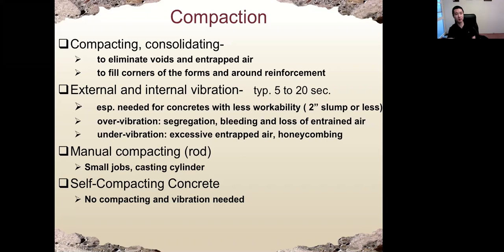However, too much compaction is also not good. It will increase the potential for segregation, which is separation of coarse aggregate and cement paste, and also bleeding - separation of water from cement paste - and loss of entrained air, the good air we put in on purpose. Under vibration, we'll have too much entrapped air, the bad air, or even honeycombing. Honeycombing is the big holes in concrete when we do not have enough vibration.